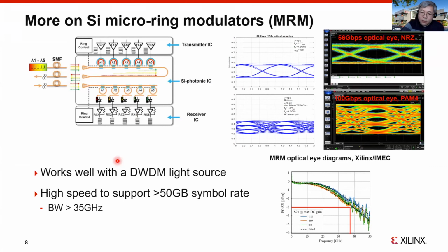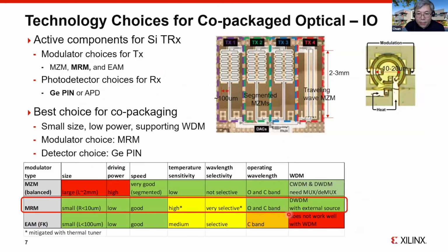If I go back to this slide, you can see that I say the micro-ring modulator actually works well with DWDM. It doesn't work with CWDM. That is because the range of wavelengths is limited by the free spectral range of the modulator, which depends on the actual modulator size. It's typically between close to 10 nanometers to maybe even over 20 nanometers, depending on the size of the modulator that you design. So that basically limits the range of wavelengths for WDM.